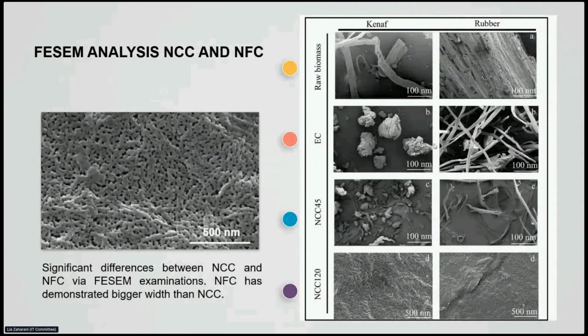For nanocrystalline cellulose, we're using different methods and different parameters. When acid concentration is the same at 48%, we're using different reaction times. When the reaction time is 45 minutes, we get a smaller dimension compared to extracted cellulose. But when we increase the reaction time to 120 minutes, that is 2 hours, we get an even smaller size. I can say it's perfect nano size.